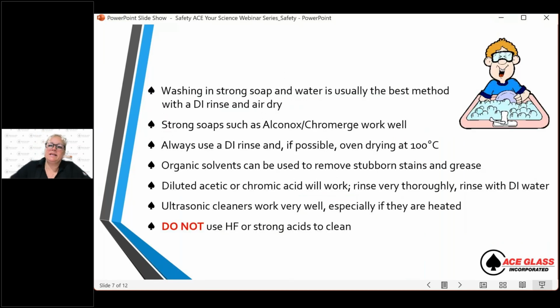So when cleaning your glassware, you should actually only wash it with a strong soap, and then rinse it with DI water and air dry it ideally. Strong soaps would be like Alconox, Chromerge, something like that would work best. If you do have organic substances in it, of course, use some solvent, maybe previous to the cleaning process, to dissolve it and get that out first before you clean it with soap.